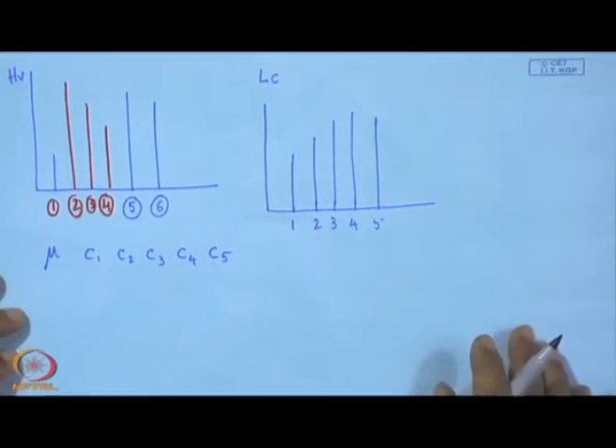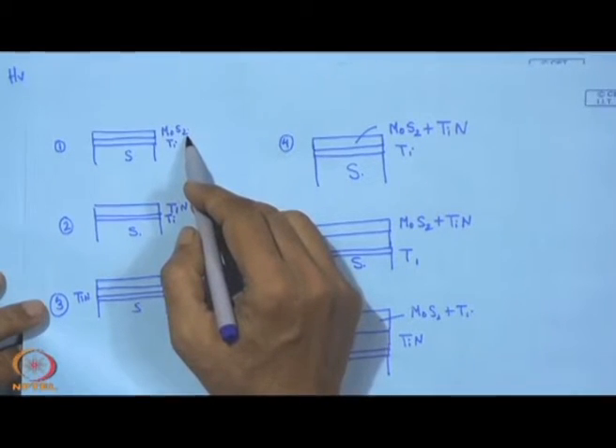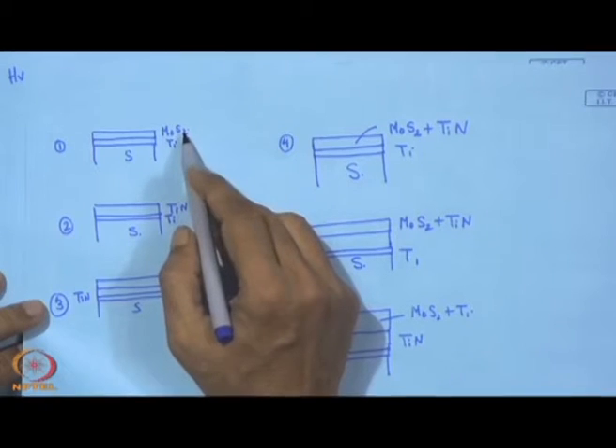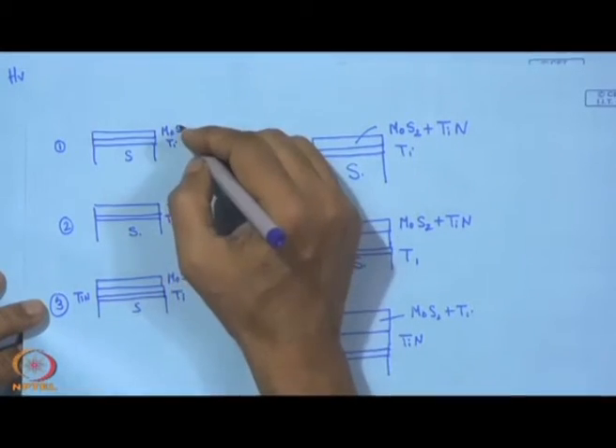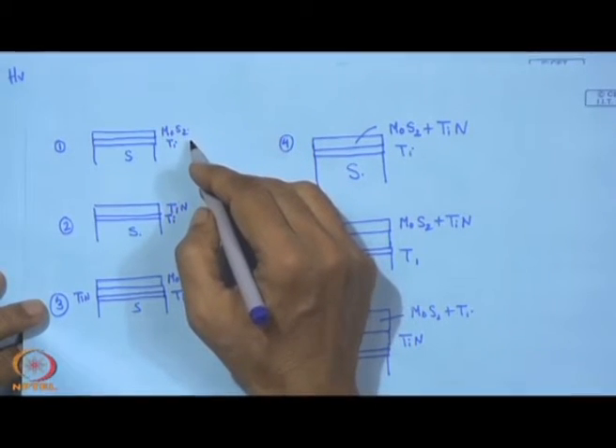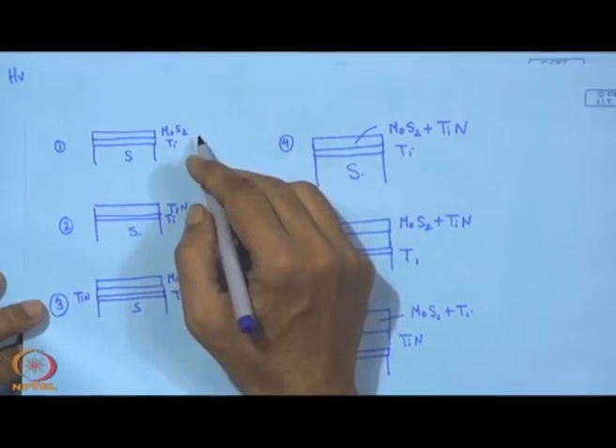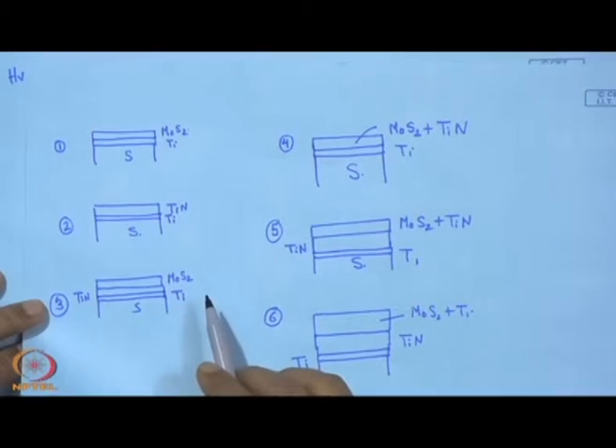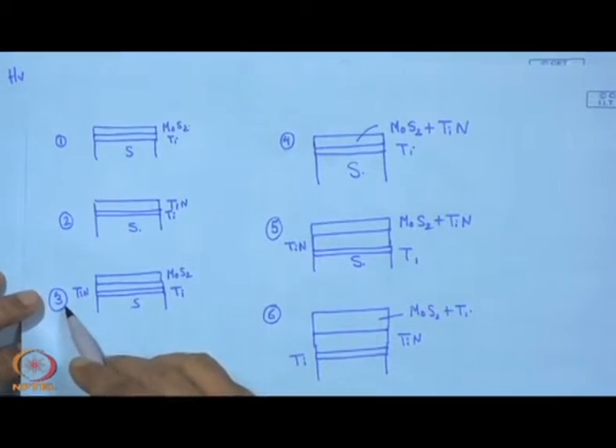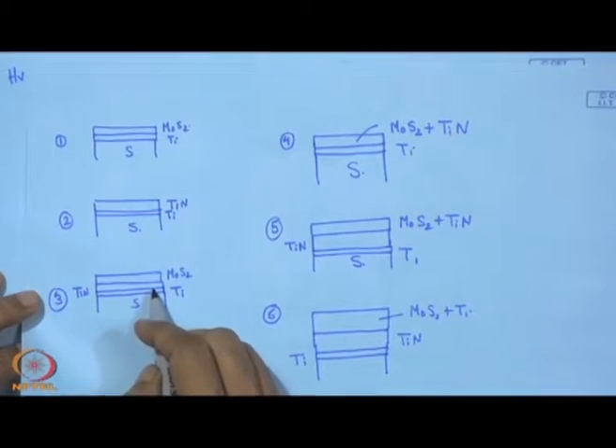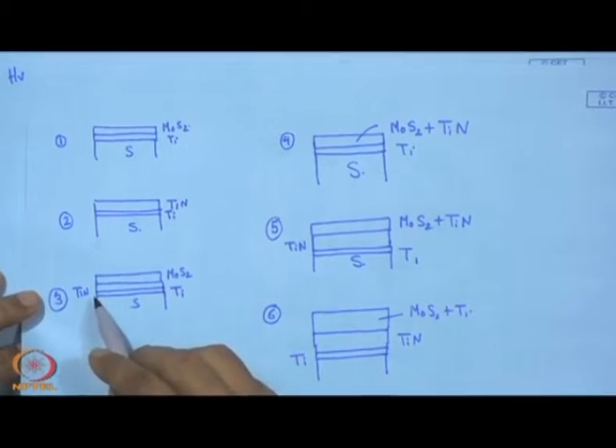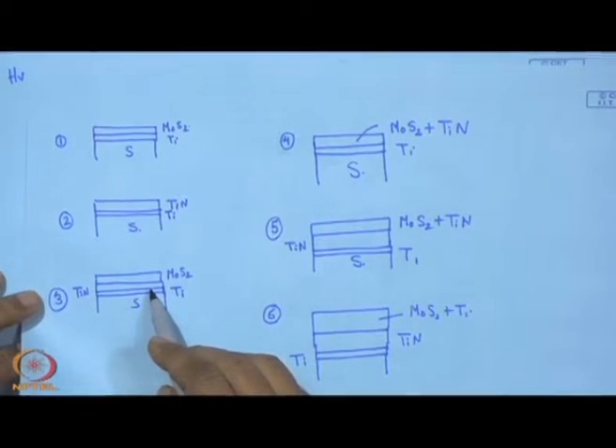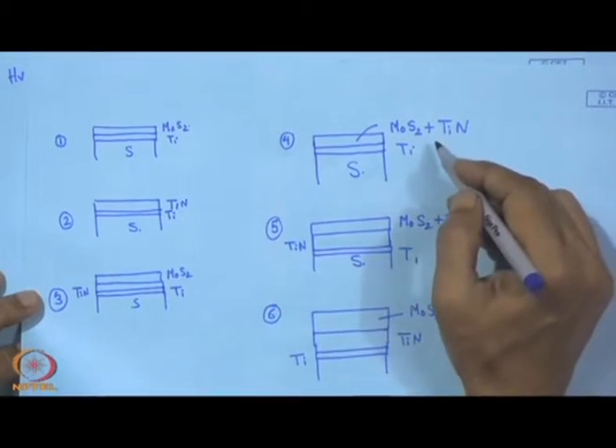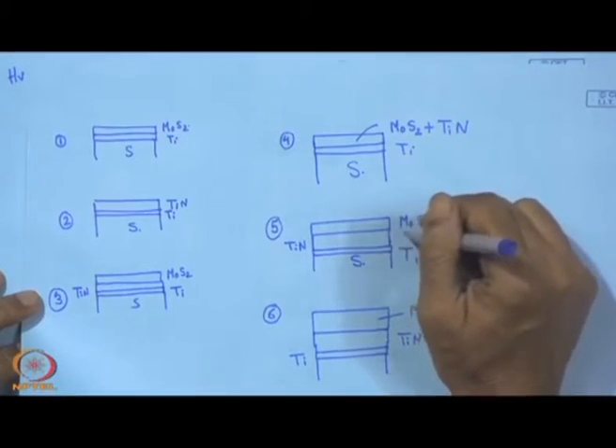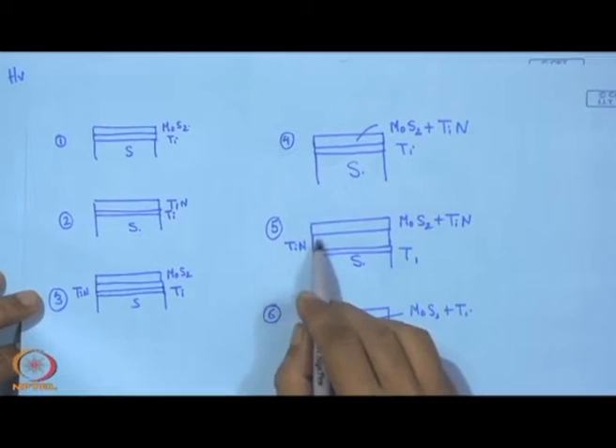Now, here obviously, since one is having just pure MoS2, from the standpoint of lubricity that is going to be the best one. However, that is short lived, that means the life of this coating is very short. However, when it is number 3 with a support of TiN, the life is actually more compared to that of this one. So, it gives a greater support. So, what we find also is that compared to this 4, 5 is a better one, and this is because of this support of TiN.